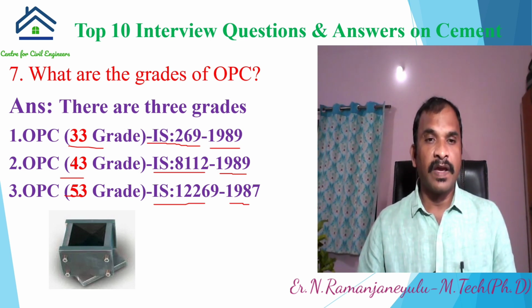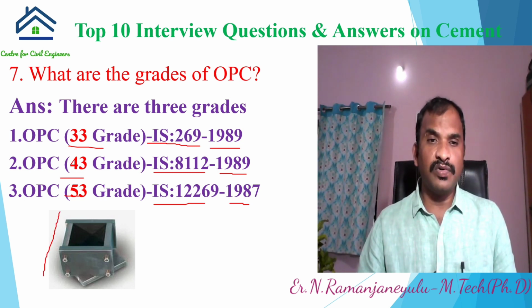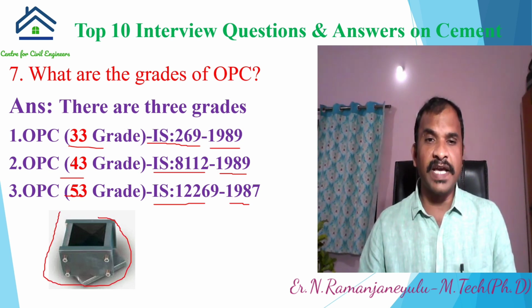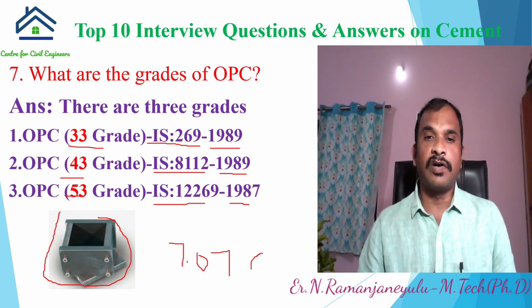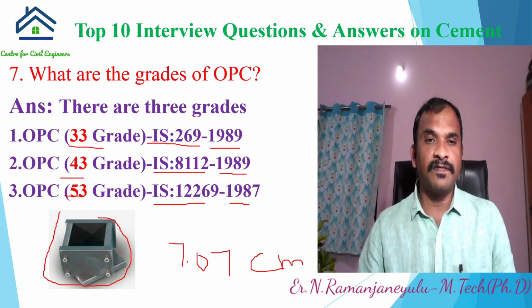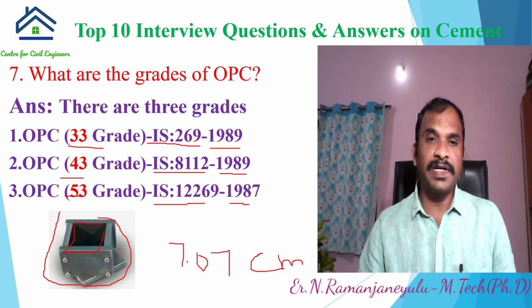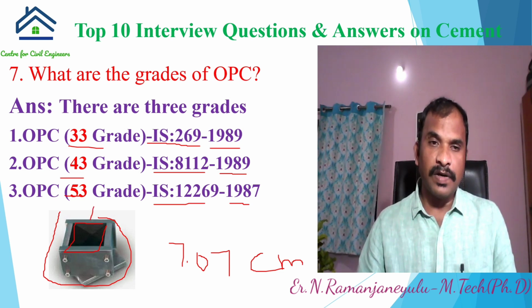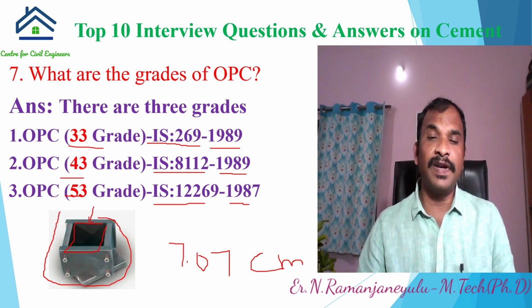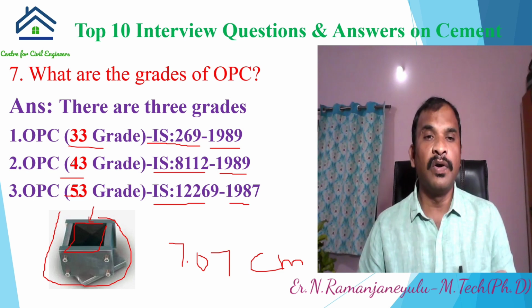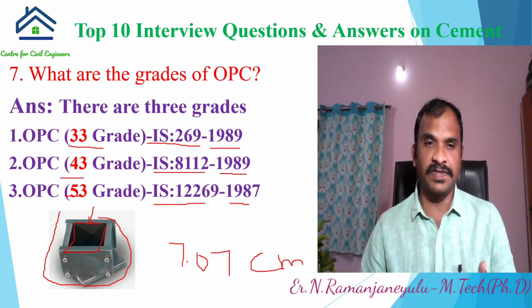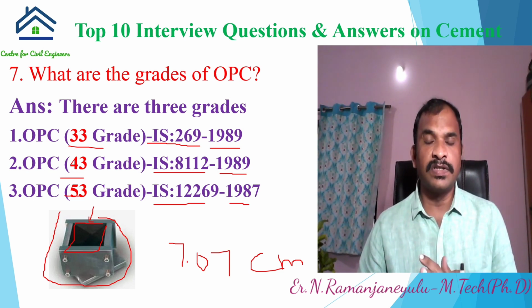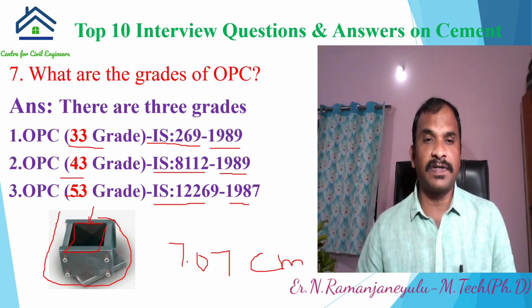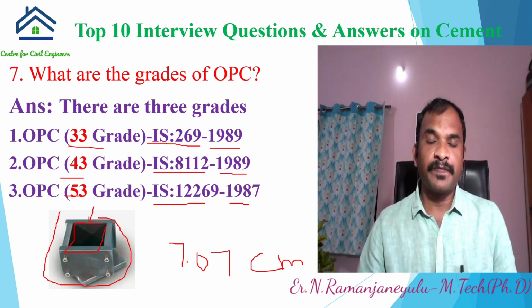If you want to test cement, we have to use this cube mold. The cube size is 7.07 centimeter, and the top surface area of this mold is 50 centimeters square. Using this mold, we have to take 3 molds, and we have to fill this mold with cement mortar of ratio 1:3, 1 part of cement, 3 parts of sand. After filling these molds, after 24 hours we have to keep in water for 28 days. Then after 28 days we have to test these specimens.